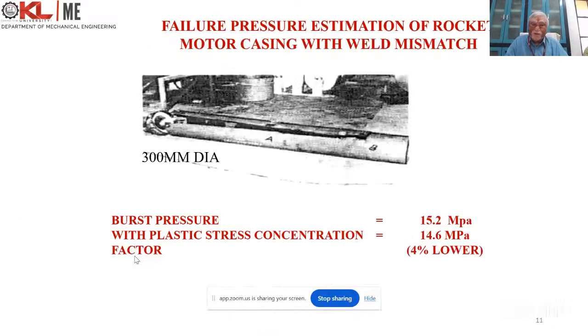Then when you are trying to roll the sheet and make the rocket motors, there will be some mismatches. The mismatch also will create a defect-type discontinuity stress, which increases the stress and reduces the load bearing capacity. So how best are we able to predict the stress concentration effect created by the mismatch? The burst pressure is 15.2 megapascal, whereas the theoretical assessment is 14.6 megapascal, 4% lower than the estimation.